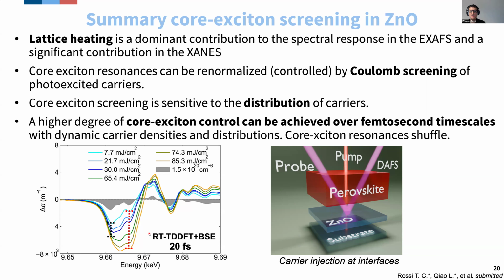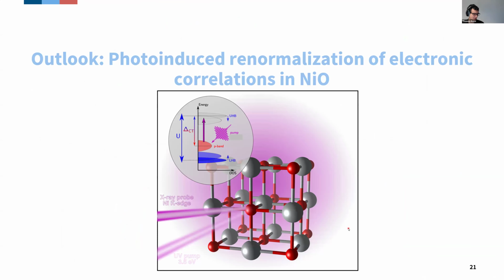And I have in mind how we could actually use these core excitons in an experiment, typically for the one that I talked about at the beginning. Now that we know that free charge carriers actually have an influence on these core excitons, we could definitely think about an experiment where we pump a perovskite layer with a laser field. This perovskite will inject electrons into the zinc oxide, and we probe, for instance, the zinc oxide at the zinc K edge, and we know that the core excitons in the zinc oxide will feel the presence of these injected carriers because they will screen the core excitons. So this is an unambiguous proof that charge carriers have been injected at the interface, basically. And that ends up the zinc oxide part.